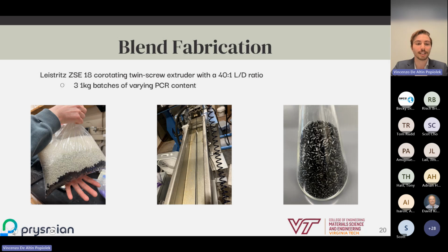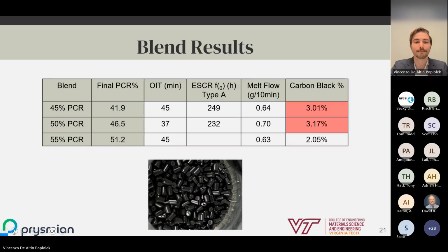One of those batches can be seen here on the left, with the top white layer being our virgin polymer, the center gray layer being our PCR, and the bottom black layer being our carbon black master batch, which contained carbon black, our antioxidant package, and then some virgin polymer to help with the compounding. In the center, you can see our polymer being extruded through a water bath to cool towards our pelletizer, which then pelletized our samples for the final product on our right.